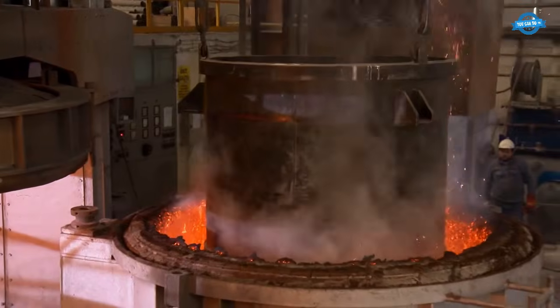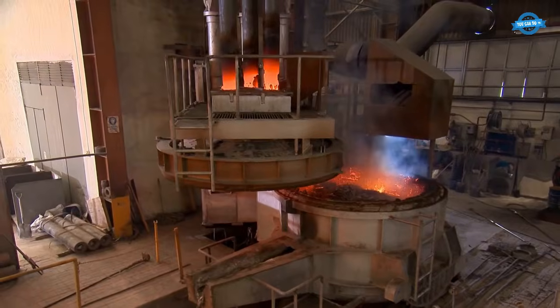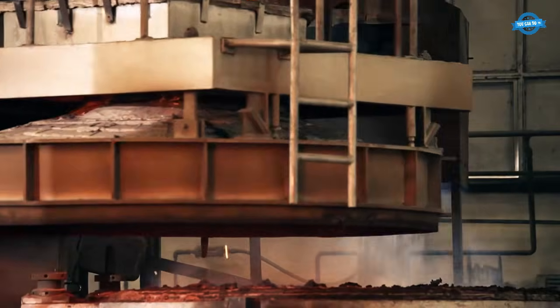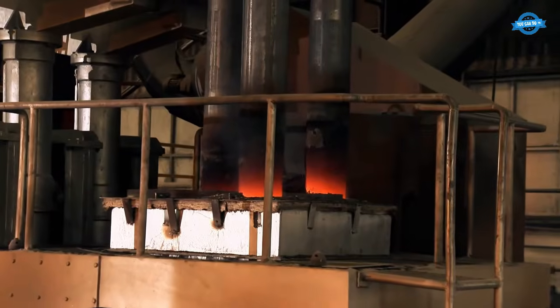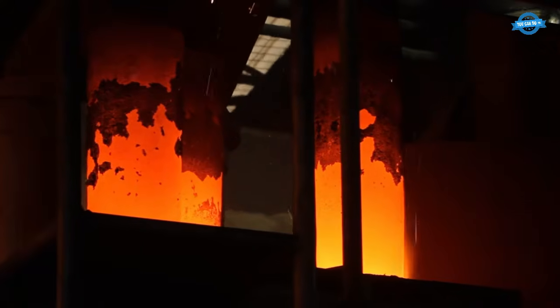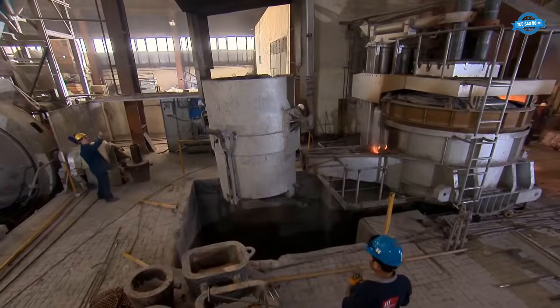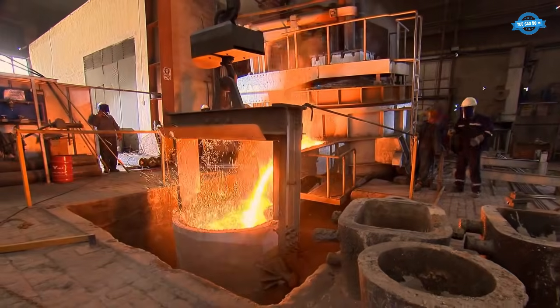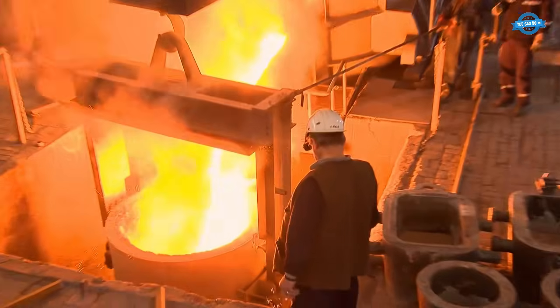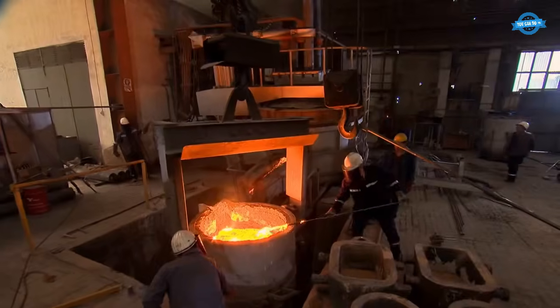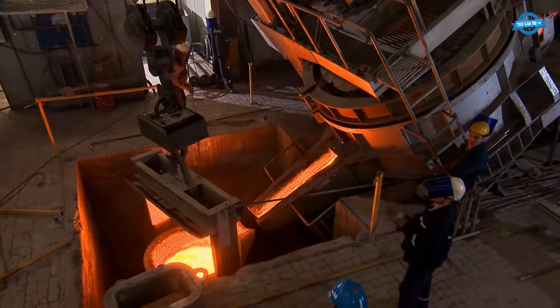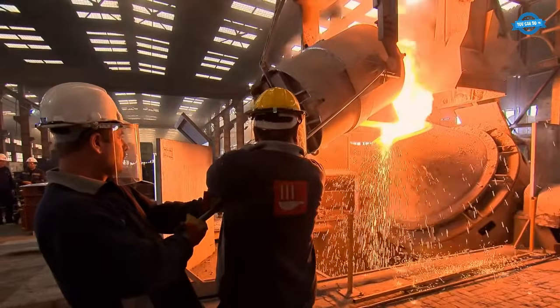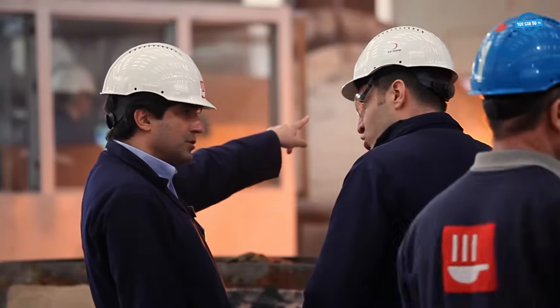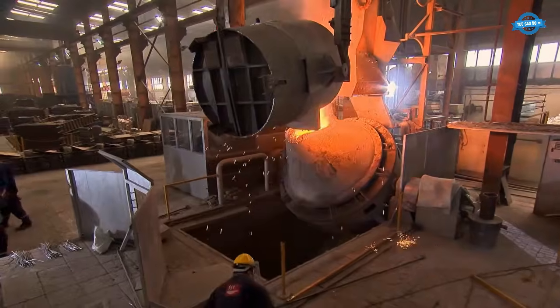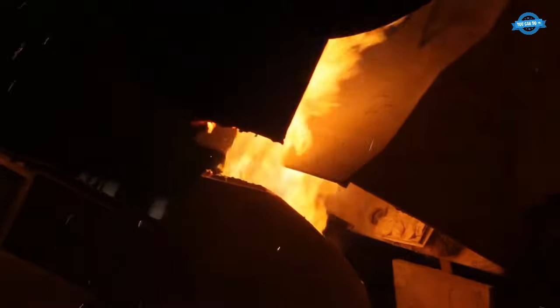The tricky bit with steel casting is that small errors do not stay small. Wrong pouring temperature, sulfur creeping above spec, moisture in the mold. Any of it produces internal defects that ultrasonic testing eventually finds after the machining is already done, which means the metal already ate a week of somebody's schedule before revealing it was scrap. Flexible production lets one facility handle both single-piece orders and 1,000-unit runs on the same equipment, retooled between jobs. That flexibility is why heavy-duty automotive castings still come from foundries like these, decade after decade.